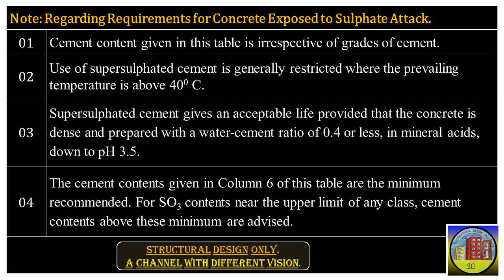Note 3: Supersulfated cement gives an acceptable life provided that the concrete is dense and prepared with a water-cement ratio of 0.4 or less, in mineral acids, down to pH 3.5. Note 4: The cement contents given in column 6 of this table are the minimum recommended. For sulfate contents near the upper limit of any class, cement contents above these minimum are advised.